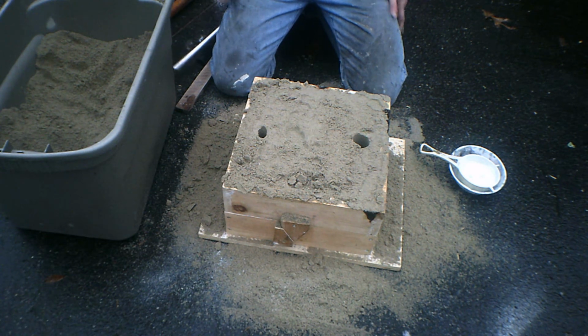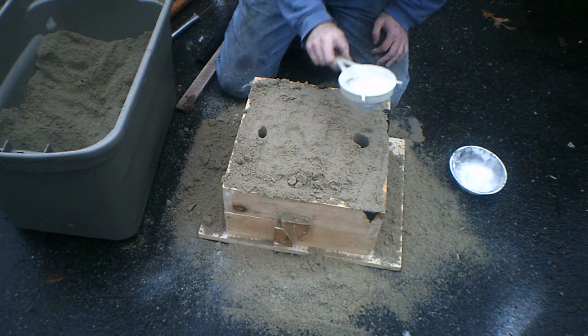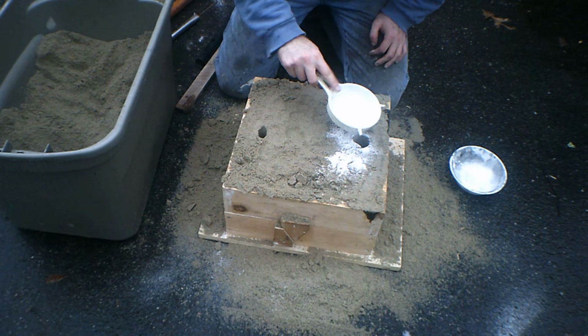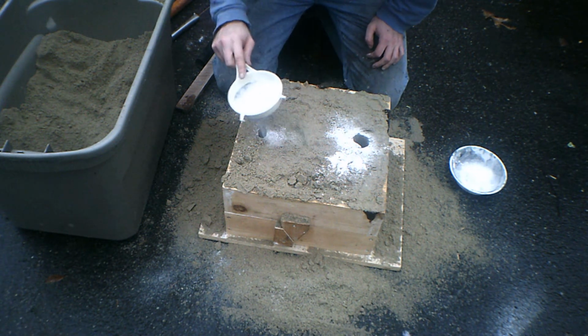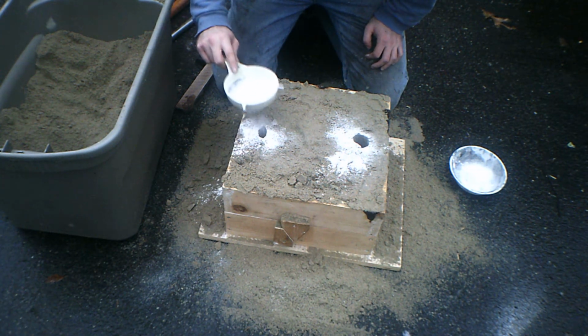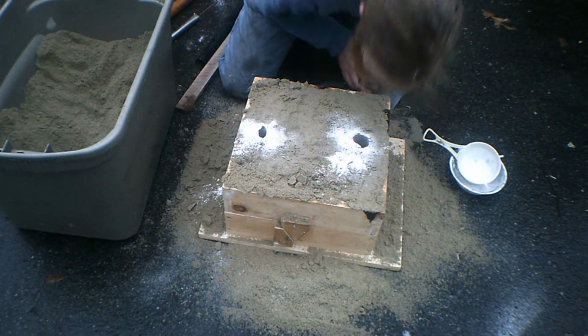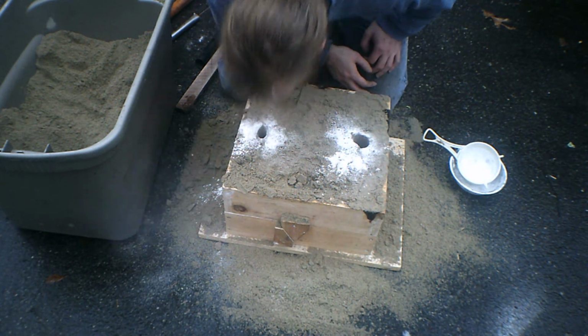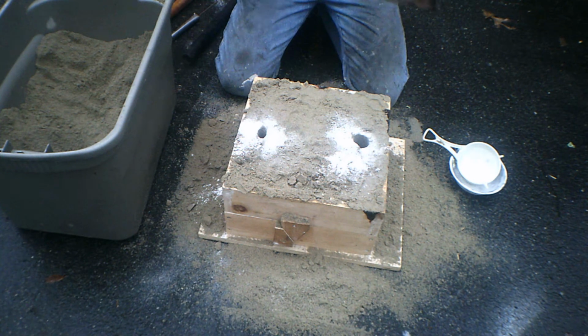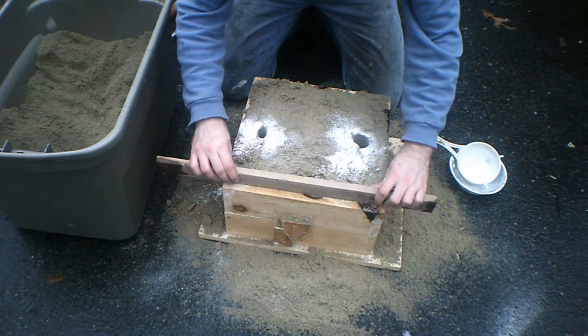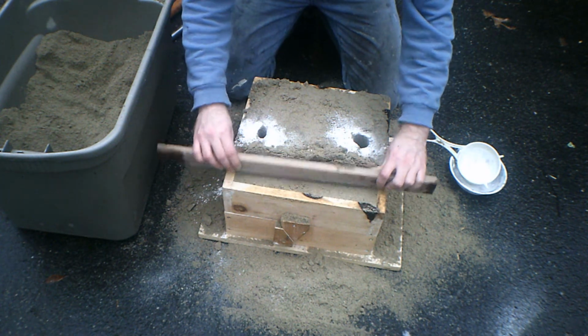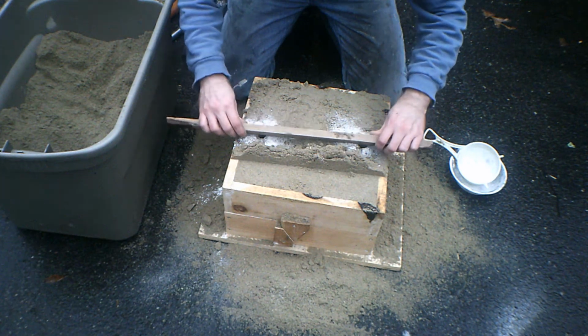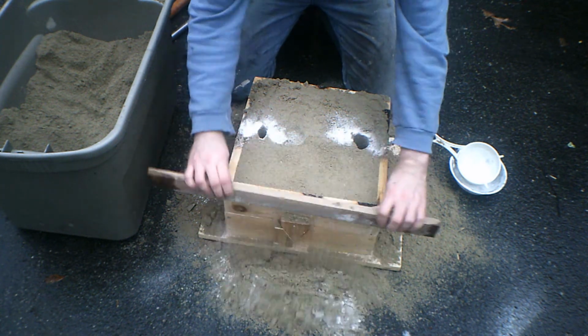Some folk like striking off with the sprue and riser pipes still intact so that they can't knock sand anywhere, but it's much easier just to dust the sprue and riser with parting compound. That way, by putting that in there and then blowing it around so it sticks to the sides, you don't have to worry about any of the sand that falls in, because it will happen anyway, sticking. Any sand that is loose in the mold will wind up being an inclusion in the finished part.